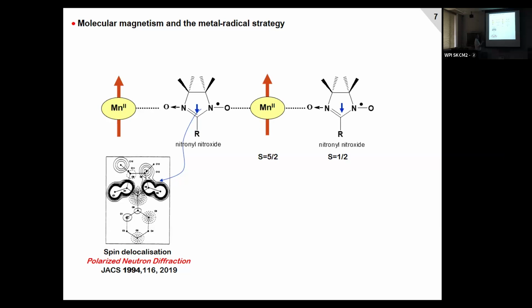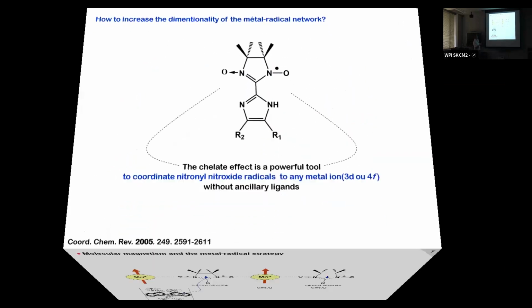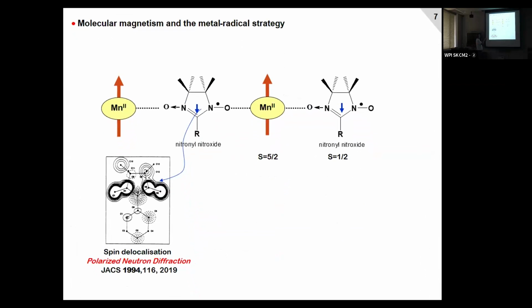So you can connect metal ions. I use also here manganese 2, because manganese 2 has the most unpaired electrons, 5 electrons. So 5 electrons means large spin, 5 halves. The radical has only 1 electron, so spin 1 half. So you have a big spin, big moment, and a small moment, and even if they are antiferromagnetically coupled, you will have a resultant magnetic moment. But finally, when I say this, they are very interesting bridging ligands, but it's not so perfect.